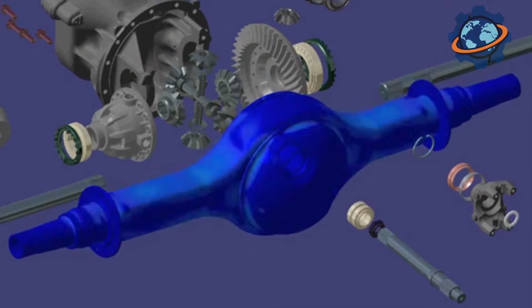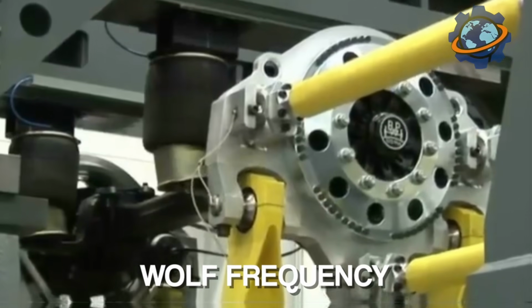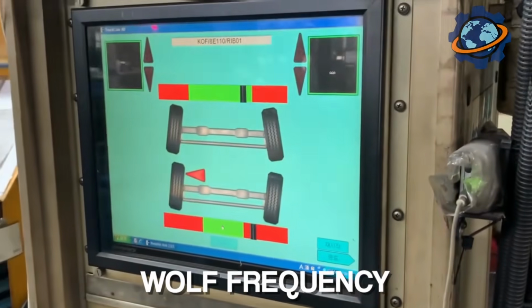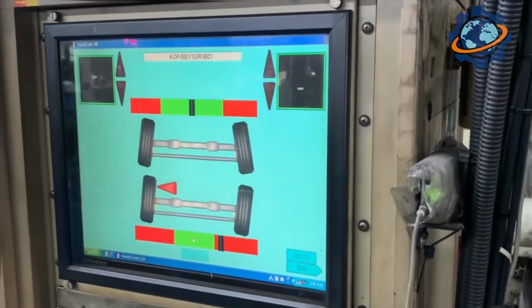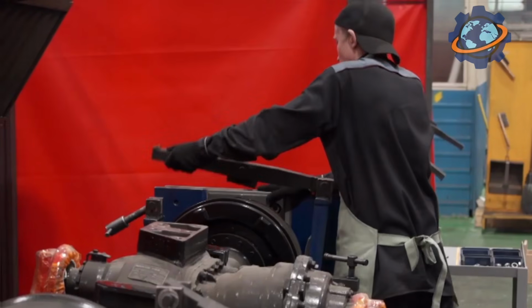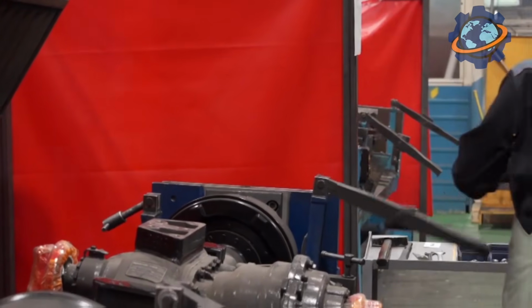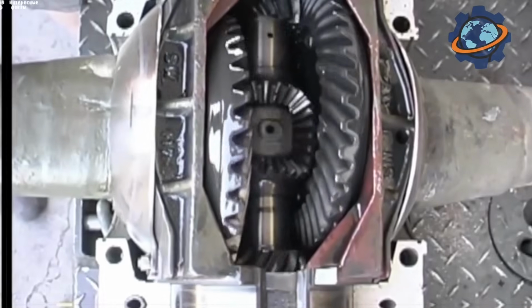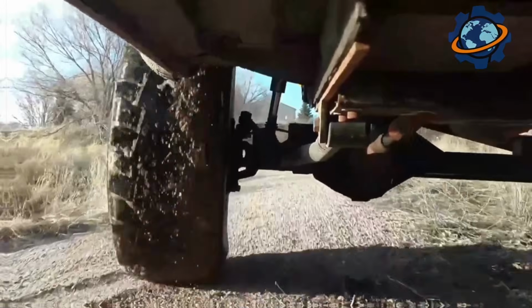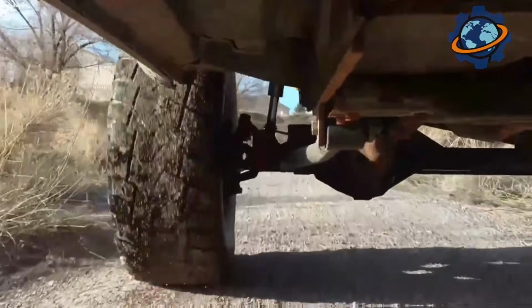A characteristic howling sound, the so-called wolf frequency, indicates improper contact pattern or deviation in tooth profile. If the microphone picks it up, the axle gets disassembled and the cause is found, because on the road, that sound will only get worse, and the problem won't just disappear on its own.